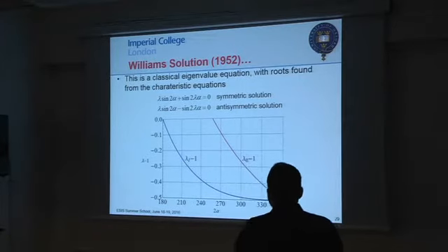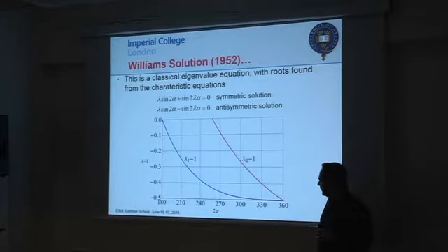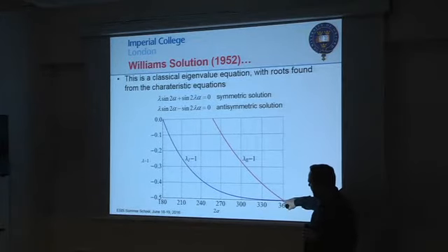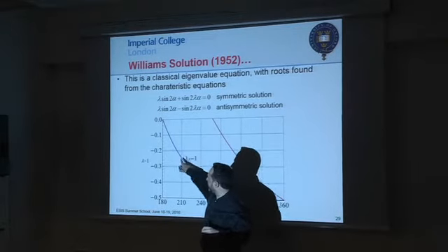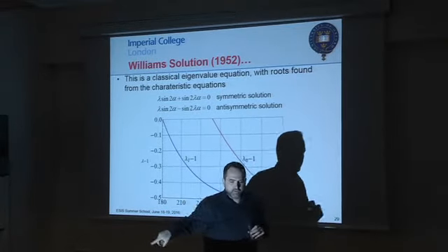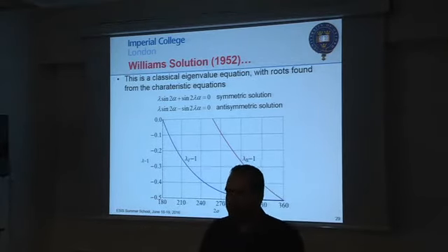Now, the intrinsic nature of this problem tells you another thing. It tells you that anywhere you are, if lambda 1 minus 1 is always negative, you always have a singular solution. So the solution is singular in nature.